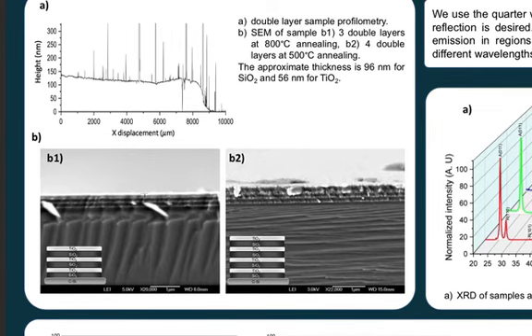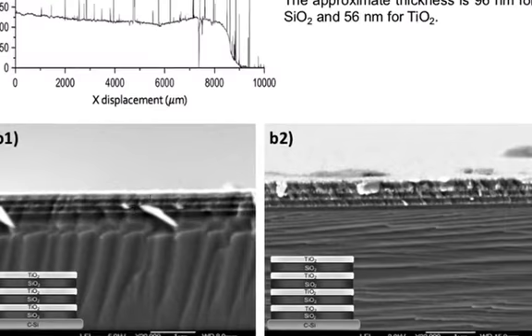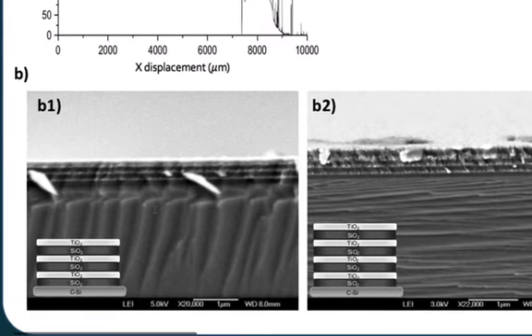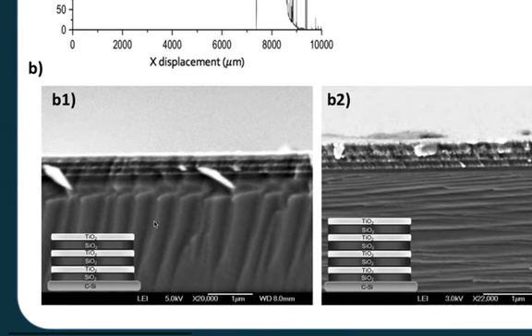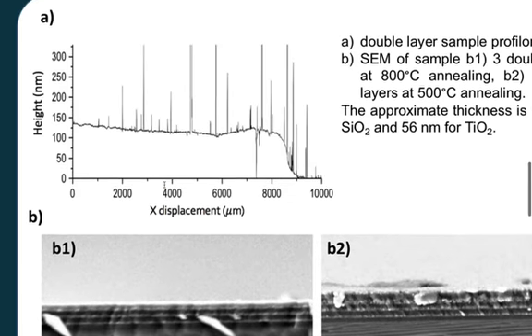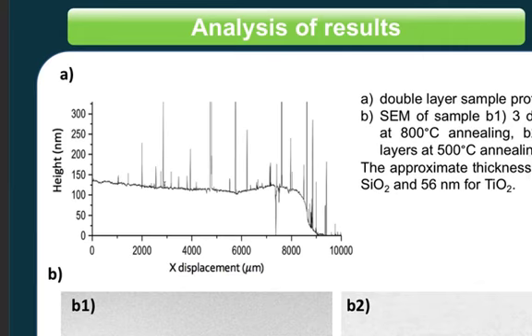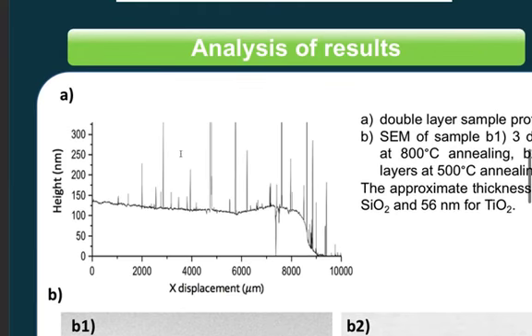In the micrograph, we can observe the growth of alternate layers with nanometric thickness. It is shown by profilometry that the surface does not vary considerably in thickness on the measurable line.